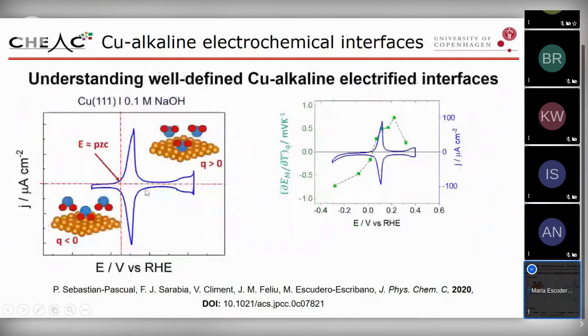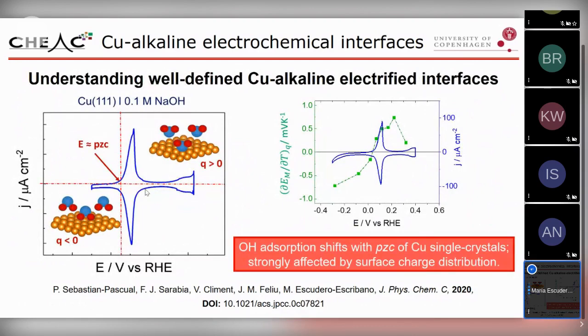copper 111. In summary, what this tells us is that this feature, which is structure sensitive, the OH adsorption, is going to shift with the potential of zero charge. As you saw before, the potential of zero charge is very different for copper 111 and copper 100. And this is going to be very affected by the surface charge distribution. So this is very fundamental work that gives information on the structure of our electrochemical interface,